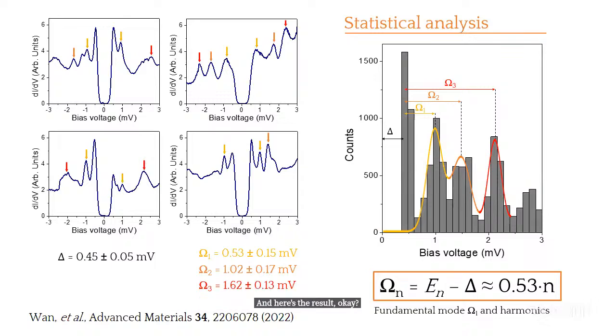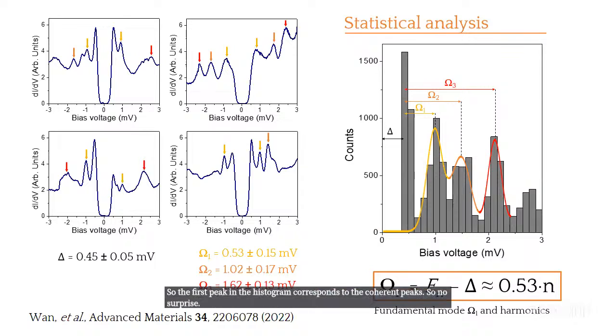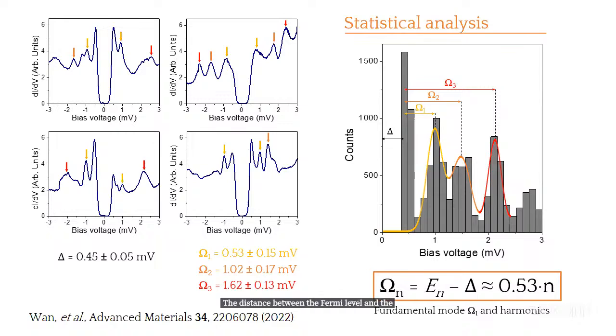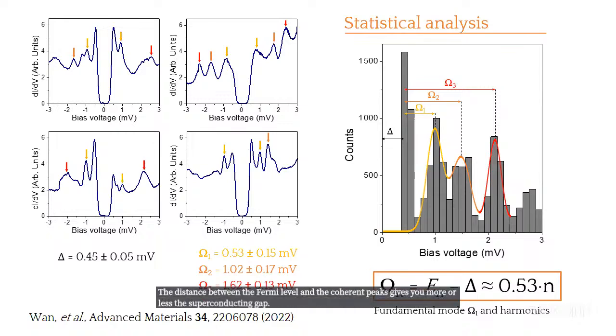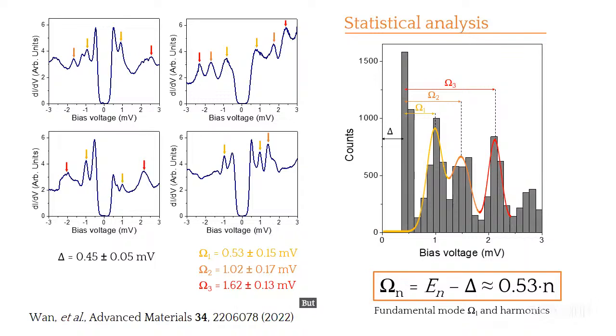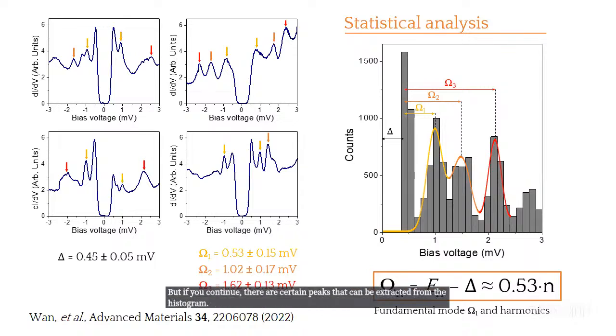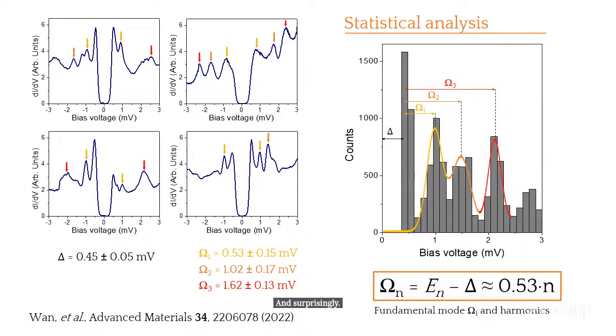So the first peak in the histogram corresponds to the coherence peaks. No surprise, the distance between the Fermi level and the coherence peaks gives you more or less the superconducting gap, which is around 0.4 millielectronvolts. But if you continue, there are certain peaks that can be extracted from the histogram. And surprisingly, we saw the position of the maxima at these energies, 0.5, 1, and around 1.5 millielectronvolts. But it seems as if there was a fundamental mode and some harmonics followed after that. So what's the origin of these peaks?